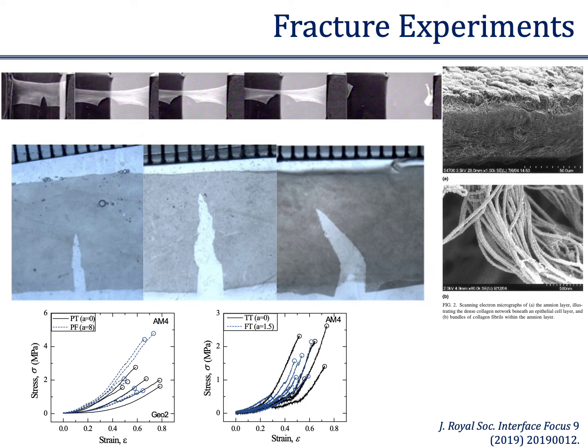In the case of the trouser tear, there's a simplified analysis that works quite well. These are pictures of the amnion in the process of cracking. So these are cases where we've introduced a notch with a scalpel, as you can see in the pictures, and then propagated the notch. As you can see, there's a significant difference between the smoothness of the scalpel cuts and the roughness of the ruptures as the crack propagates through this collagen network. And interestingly, when we look at the raw data for our specimens, there's actually not a significant difference between the stress-strain response as we pull on these specimens, regardless of whether they have a notch cut in them or not.